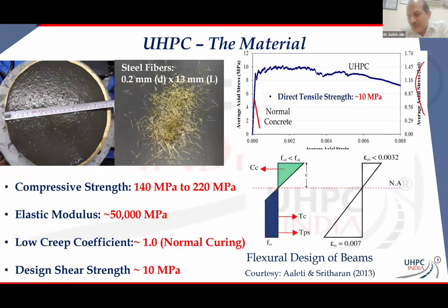And that is why sometimes, when people say that there's hardly any reinforcing in UHPC or there might be no reinforcing in UHPC, the reason is that you do get a significant amount of capacity building out of the UHPC in tension as well. Of course, at the same point of time, I would say if you have pre-stressing and rebar along with it, you can have any permutation combination that you want to have to get a more efficient design.